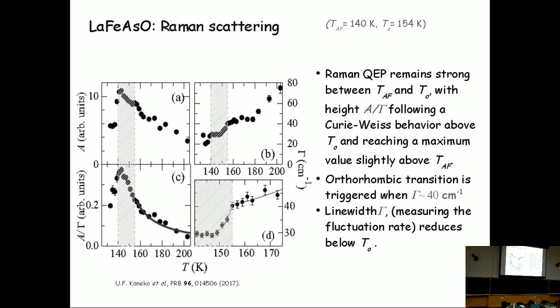So that's unexpected. Also unexpected is the fact that this width goes down, meaning that you have fluctuations which are less dynamic, getting slower as you cool down. And then you see that at the structural transition temperature, these fluctuations experience not a freezing, but they get slower, let's say that. So the surprising observation here is that this structural transition apparently doesn't appear to be the critical temperature for the nematic fluctuations that we're seeing by Raman scattering, but these nematic fluctuations are still seeing the orthorhombic transition. I mean, they get slower when you get into the orthorhombic phase.